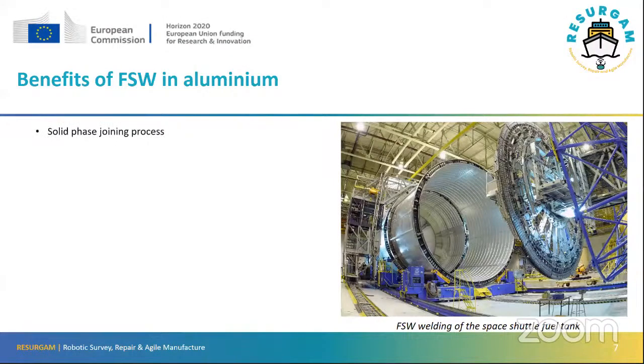It's been around for about 30 years and is widely used in a lot of industries. So this particular image shows the space shuttle fuel tank, which was fully friction stir welded. The benefit of the process is that it can allow you to make a very good single pass weld up to 75 millimeters thick in aluminium.